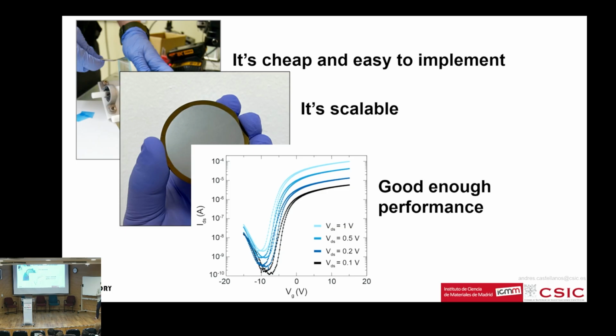So, of course, single flake mechanical exfoliated deterministic transfer is going to be the champion kind of device. Chemical vapor deposition is going to give better performance than the ones that we get with this roll-to-roll. But this is better, for example, than the typical films people produce with liquid phase exfoliation. So it's something in between chemical vapor deposition and liquid phase, with the advantage that it's as cheap and easy as liquid phase exfoliation, and it's completely dry. No liquid solvents, no nasty chemicals.